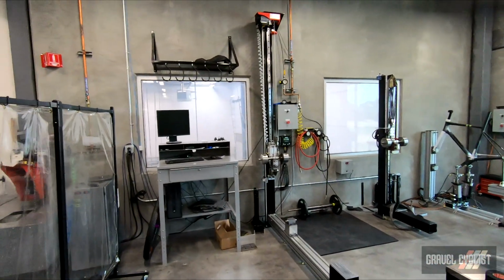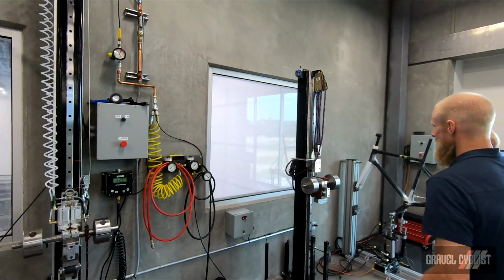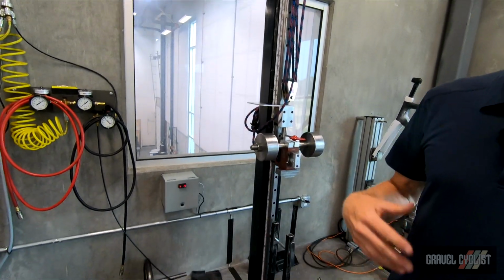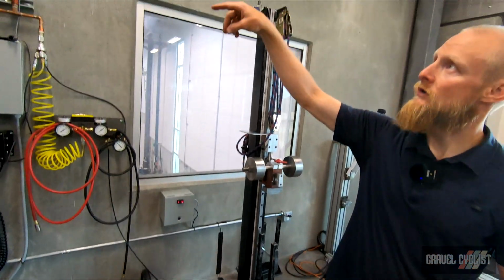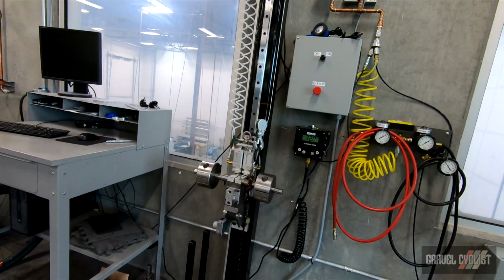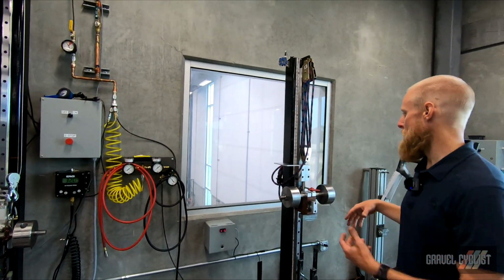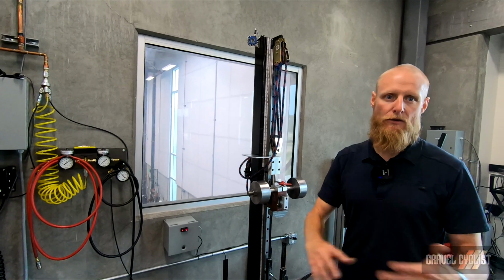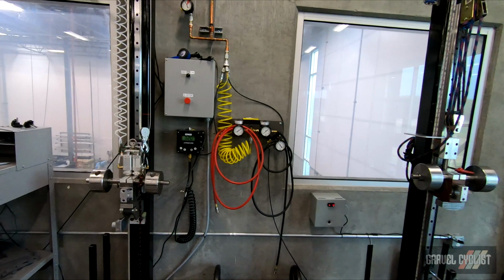These two towers here are impact test fixtures. This one here is the original, the shorter one. Due to the progression we've had with mountain wheels over the years and making them stronger, we actually had to build the new test fixture because, with this one, the rim strength was exceeding the abilities of the fixture to break them, and we didn't want to start over. I mean, we could simply add more weight to it, but then we're starting with a whole new baseline of a test. So new test fixture to do impacts, and then the impact test eventually breaks the rim, and that's where it ends.